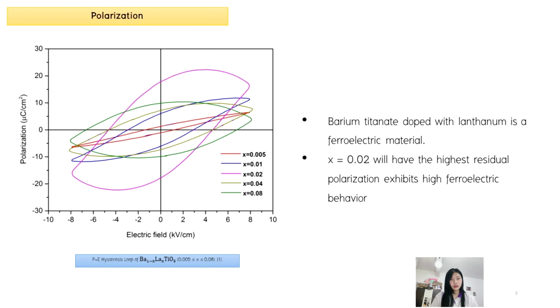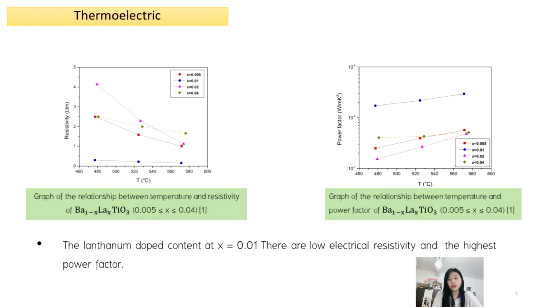This is the hysteresis loop of barium titanate doped with lanthanum, and it is a ferroelectric material, and x equals 0.02 has the highest remnant polarization, exhibiting high ferroelectric behavior. You can see the graph of the relationship between temperature and resistivity, and the graph of the relationship between temperature and power factor of barium titanate doped with lanthanum. The lanthanum doping content at x equals 0.01 has low electrical resistivity and the highest power factor.